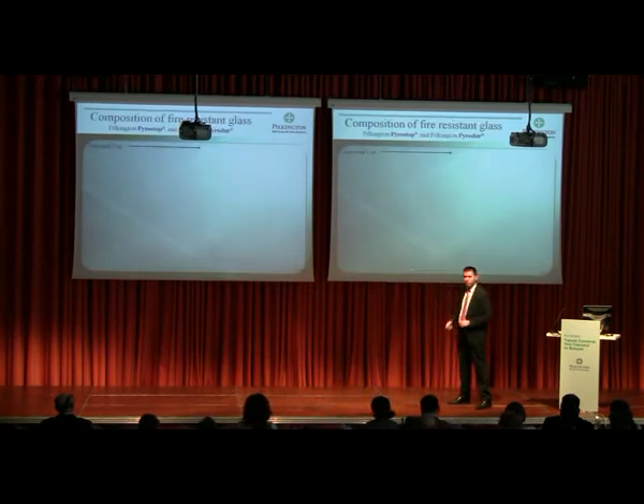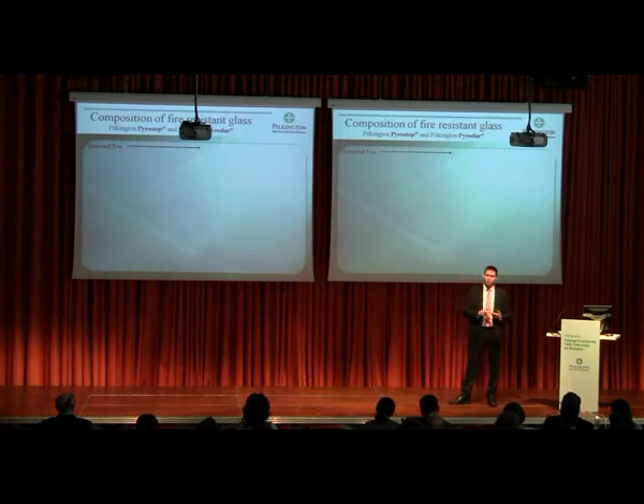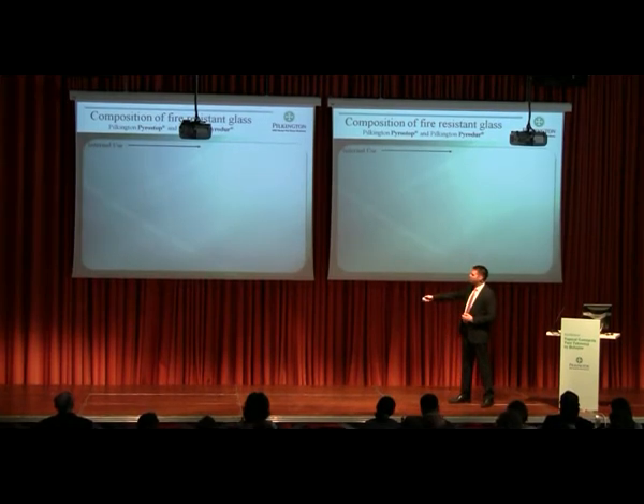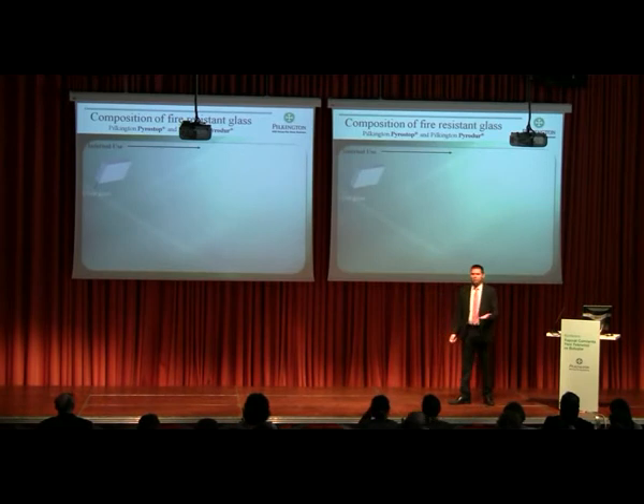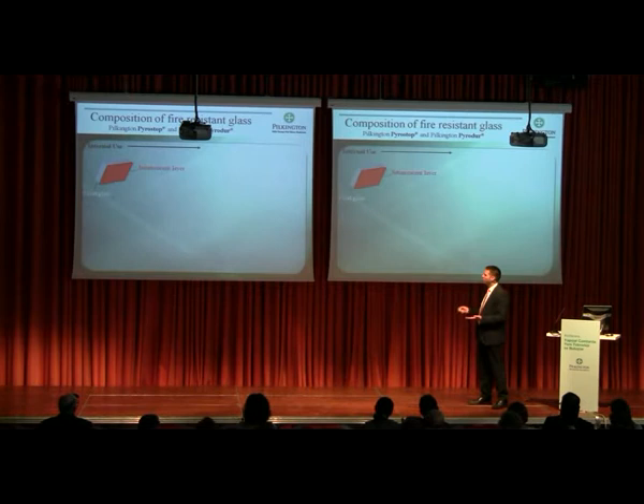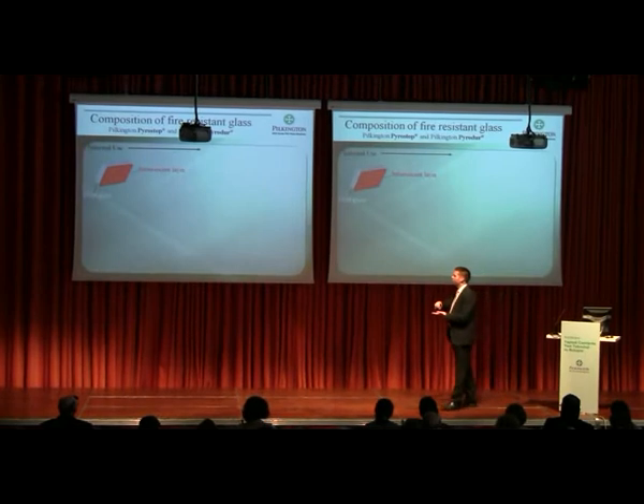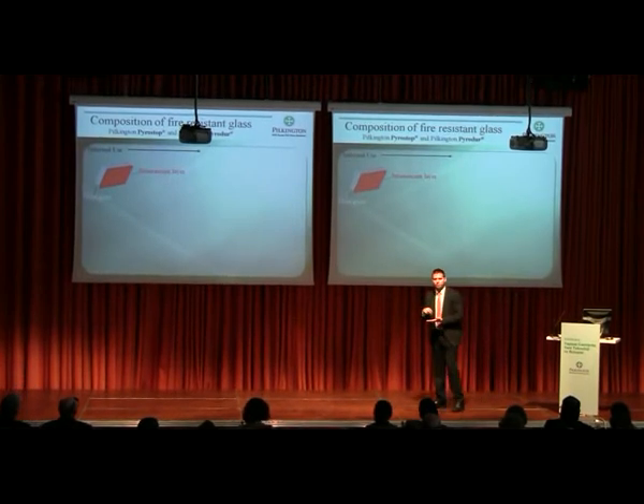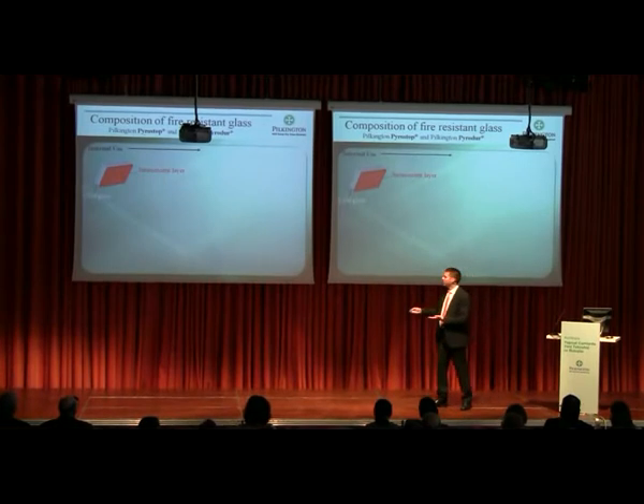And we need it. So let's come to the composition of fire-resistant glass. The composition is in general the same for the Pyrostop and the Pyrodur glass. So for the glass with total thermal insulation and for the glass with the reduced heat radiation. What we do is we use simple float glass. I just explained to you, float glass will break in case of fire, but we don't want the float glass to break. Because what we do is, we take the float glass and we fill some intumescent interlayer on that float glass. This intumescent interlayer is not visible, only if it reacts in case of fire.